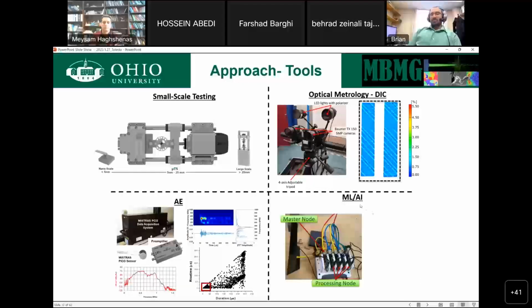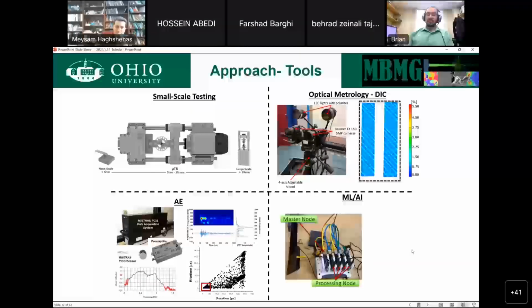And then we add into that machine learning and AI. If you think about acoustic emission, this bottom right plot in the AE section is an example of the type of data you get from one monotonic load test, about a 5-minute test, and we have all of these dots. So we have to come up with some way to handle that and be able to get meaning out of it in a reasonable time frame. We're developing a microprocessor, all based on Raspberry Pis, built in our lab upstairs, that allows us to do this type of processing as the data is being collected.